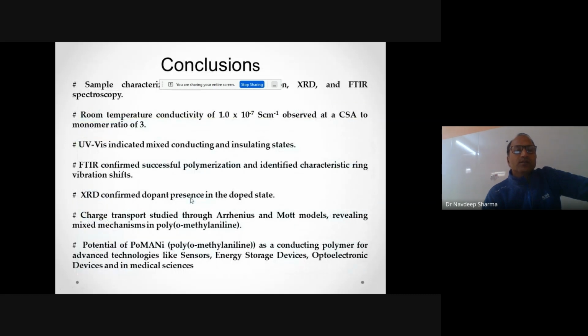And we found that the room temperature conductivity of our sample is 1.0 into 10⁻⁷ Siemens per centimeter, observed at CSA to monomer ratio 3. XRD confirmed dopant presence in the doped state, and FTIR confirmed the successful polymerization and identified the characteristic ring vibration shifts. And the charge transport study through Arrhenius and Mott models revealed a mixed mechanism in poly-orthomethyl aniline.